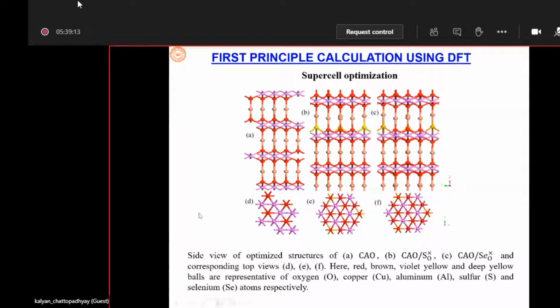The left panel is basically the pristine copper aluminum oxide. In the middle panel, you can see that we have replaced some of the oxygen atoms by sulfur atoms. These yellow atoms are sulfur, and here we have shown oxygen atoms replaced by selenium. Actually, we have also calculated some tellurium incorporation in place of oxygen, but I am not showing that result today because that experiment is not yet done. So only the sulfur and selenium doped systems at the oxygen site, remember.